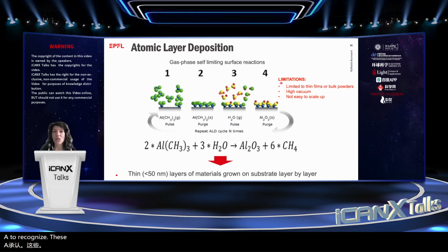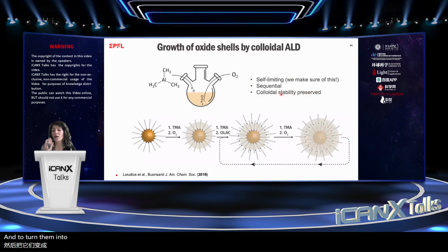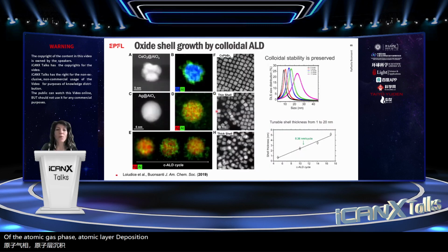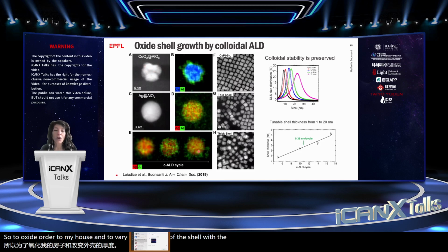And so what we did here was to recognize this limitation of atomic layer deposition and to turn it into a solution-based process. Basically, here we have our nanocrystals in a solution, and then we sequentially add trimethyl aluminum and oxygen in a similar manner to the gas phase atomic layer deposition. And we were able to demonstrate that this approach is applicable to different cores, oxides or metals, and to vary the thickness of the shell with colloidal ALD cycles.